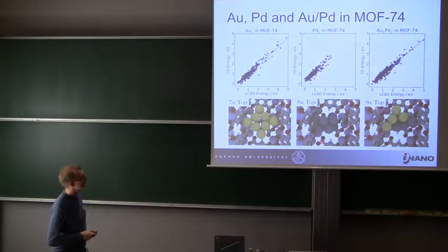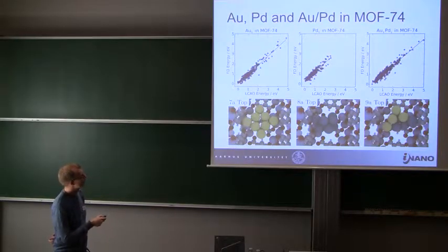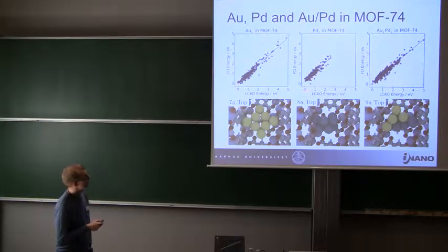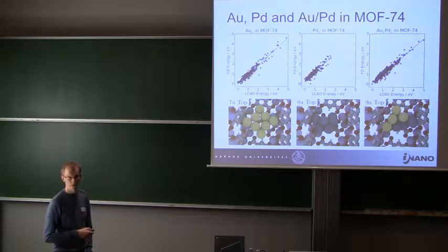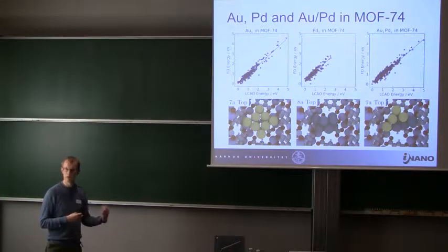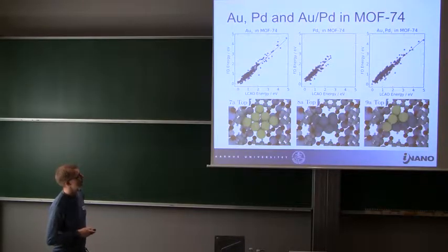I want to show this slide from where we investigated gold and palladium clusters in a metal organic framework. There's a metal organic framework here with some zinc atoms, carbon, and other types of atoms. Here are the correlations between the LCAO energy and the finite difference energy. You see there's a really nice correlation. The red line here has a slope of 1. Over here I zoomed in a bit because there's this one structure here. This is really one of the points that shows why we need to also use the finite difference basis, because there isn't a perfect correlation between the two. We only really trust this one. But since there is such good correlation, we can do the local relaxations with the LCAO basis. I think it's a surprisingly good agreement between the two methods.